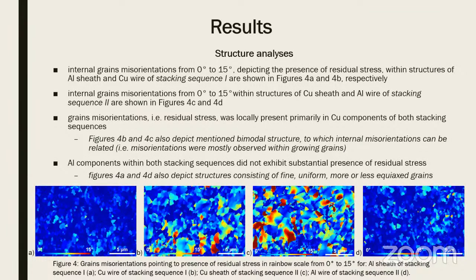In this slide we have the results of structure analysis depicting the presence of residual stress, which means we have here internal grain misorientations on a scale from 0 to 15 degrees. 0 is depicted in blue color, and then we have the rainbow scale to 15, which is red color.